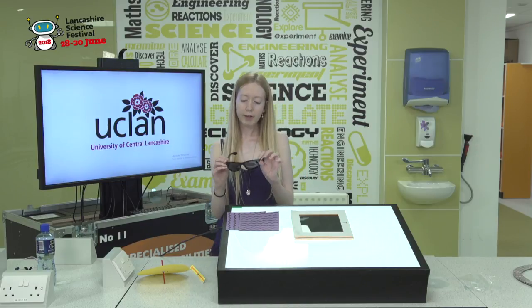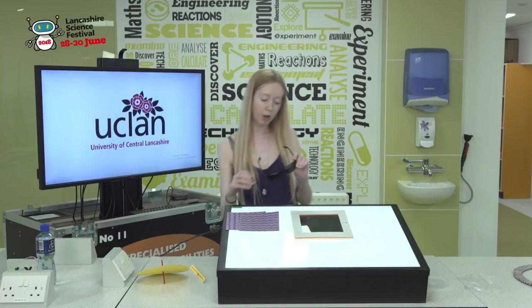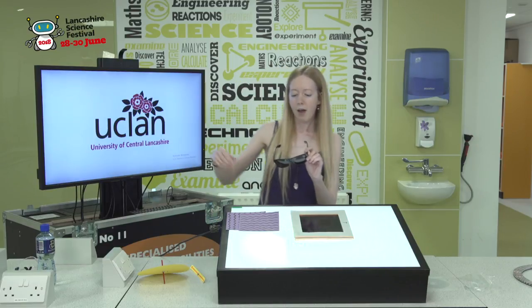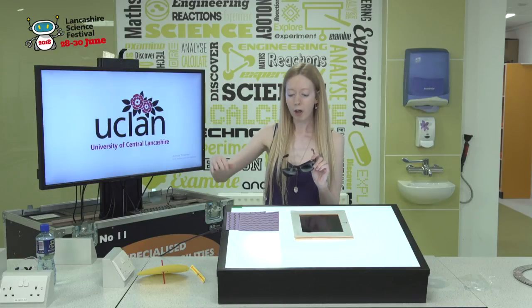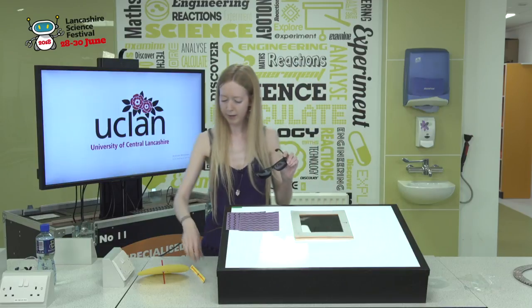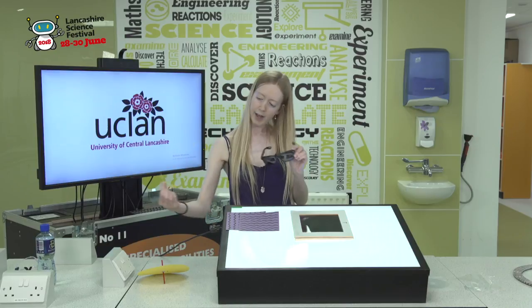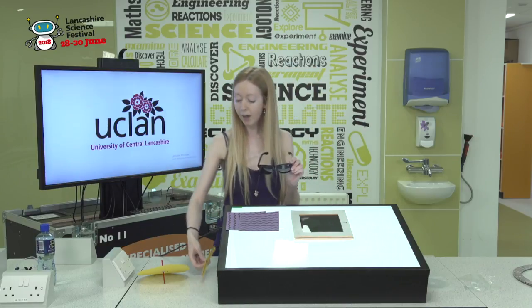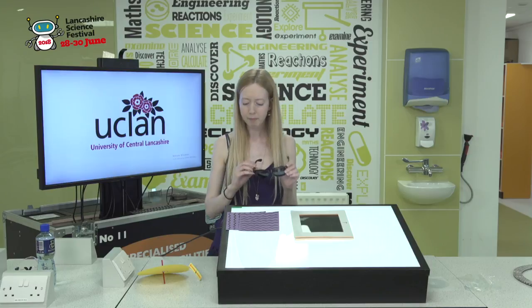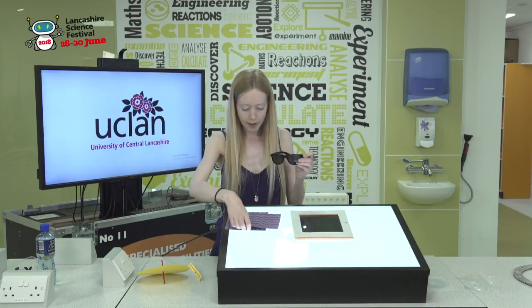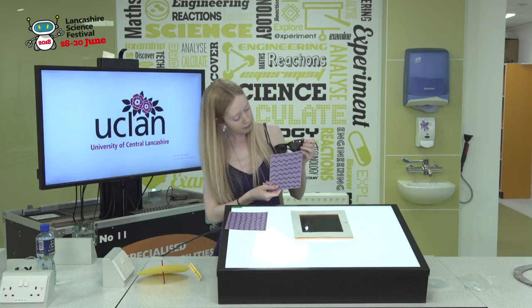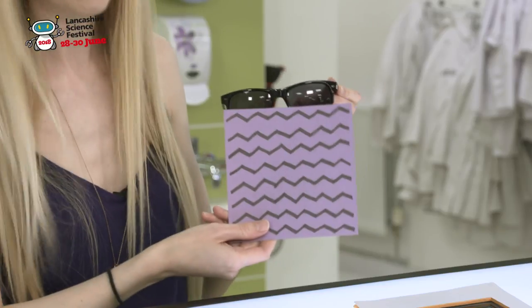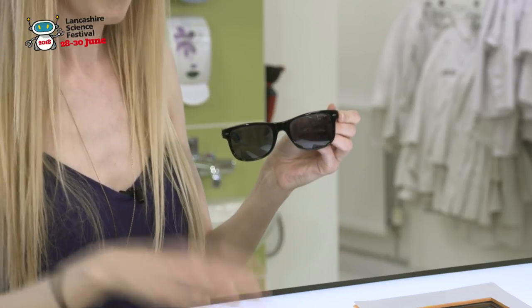So the reason why they use polarizing filters is because when you're outside on a sunny day, when the sun reflects off water or off glass, it becomes partially polarized. So you actually end up with something coming towards you like this, or polarized light coming towards you like that. And that actually produces a horrible, nasty glare. So in my polarized sunglasses, I actually have chains of molecules that look like this, and they actually absorb that polarized light that's coming towards you, and that cuts out that nasty glare.